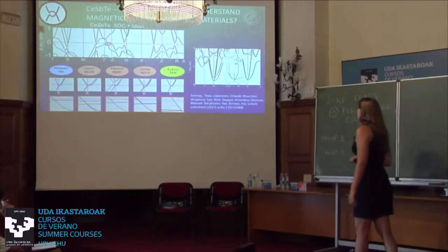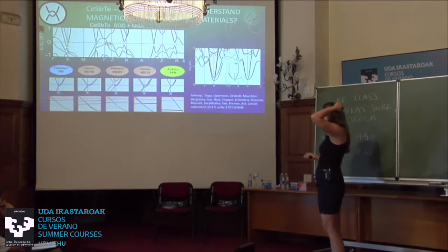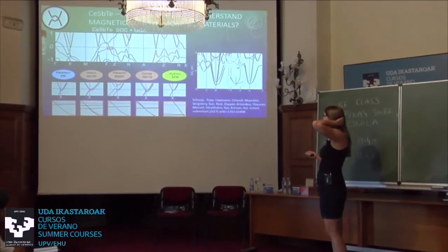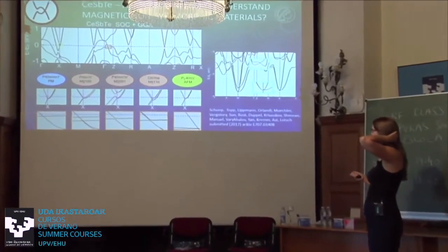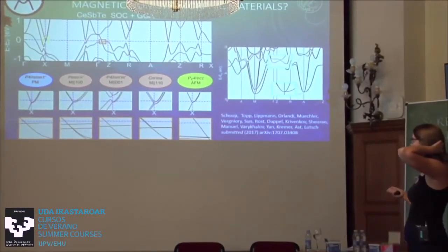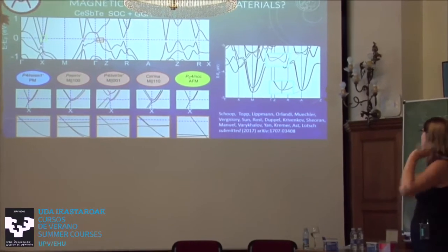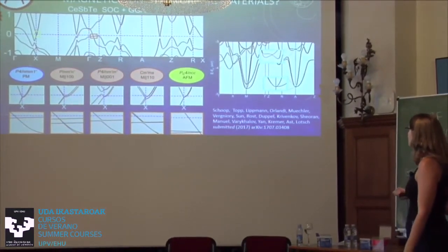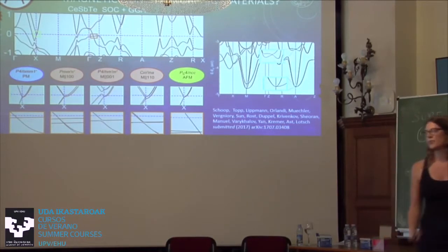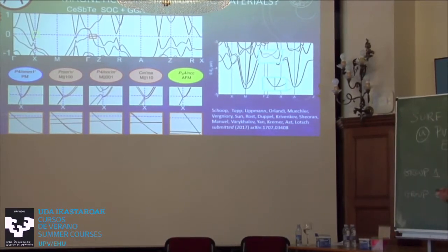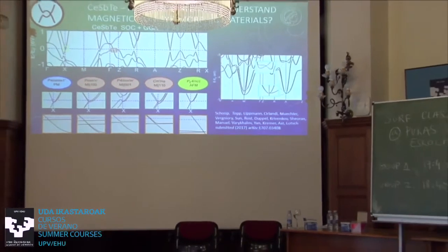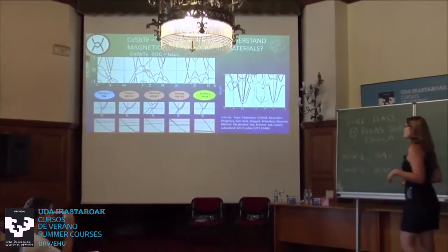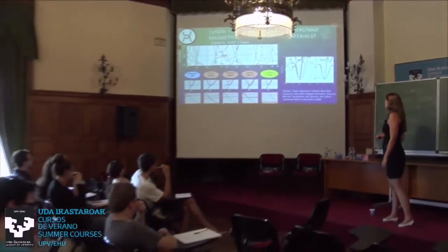And so here we could verify all the group theory predictions Maia did with the DFT. So we see the splitting, for example, here at the X point into twofolds if we apply a ferromagnetic case, and we find the eightfold degenerate point at the A point, sadly very far away from the Fermi level, so it's not yet applicable, but we're just starting with this idea of using antiferromagnetic order for this, so we can use this in the future.